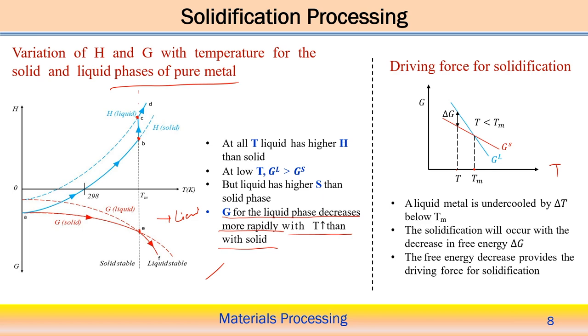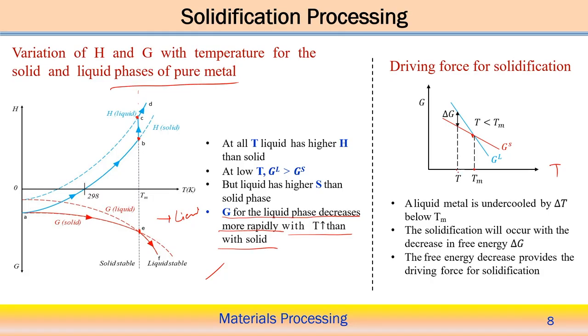Now, we have seen that in the solidification process the undercooling is one important feature to look into, that actually is the driving force for the nucleation. That means this undercooling is required to start the nucleation process, transforming from the liquid phase to the solid phase. So, here you can see that even less than the melting point, or below the melting point temperature, this is the change of the Gibbs free energy corresponding to that. And above the melting point temperature, you see the Gibbs free energy for the liquid phase is lower as compared to the solid phase. So, here the liquid phase is more stable.